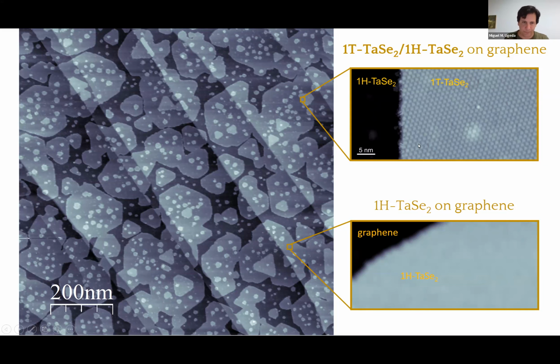Can I ask, Miguel, do you do anything with the growth to change between the phases, or is it just a natural preference for 1T growing on top of 1H? So you have to play a little bit with the temperature. I didn't mention that. I think in tantalum diselenide it's relatively easy to get the 1T phase, whereas, for example, in niobium diselenide it is really hard. So you have to go to really high temperatures in order to have the T phase. In tantalum diselenide it's easier, but yet you have to go to slightly higher substrate temperatures during the growth in order to get a significant fraction of the T phase.